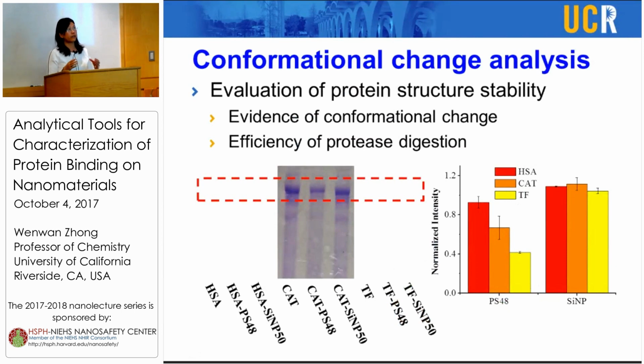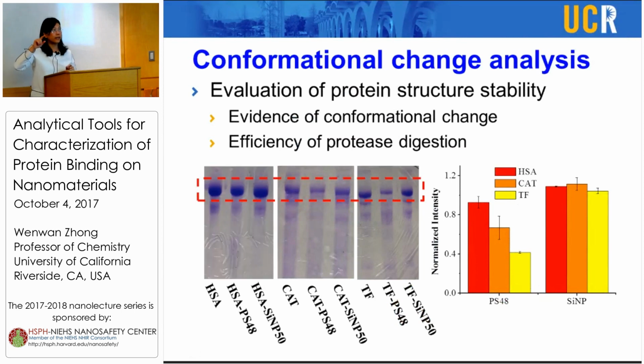This protease digestion is very quick. We only conduct a 5 minute digestion with trypsin, and then we see that if the protein is incubated with the particle, some of the proteins showing high fluorescence change are indeed digested much more rapidly than the proteins showing very low fluorescence change. For example, the first batch of the gel, 3 columns, is human serum albumin, which shows very low fluorescence change. But catalase, CAT, and also transferrin both show very high fluorescence change.